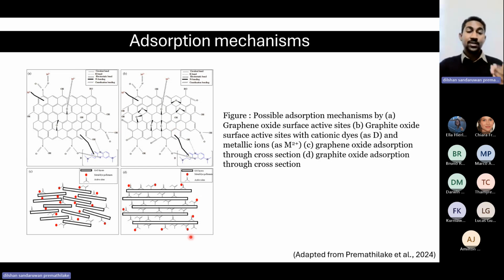But if you see the cross section in figures C and D, in figure C the graphene oxide layers are fragmented, so there are more cavities inside. More pollutants can penetrate into this and get trapped inside these cavities. This is why graphene oxide adsorption is quite high in each of the cases compared to graphite oxide. On the other hand, the graphite oxide only attaches to the surface active groups presenting on the surface and at the end of each layer. So I think graphene oxide is better in many aspects than graphite oxide for these reasons. It's fast, and it can also contain more pollutants inside.